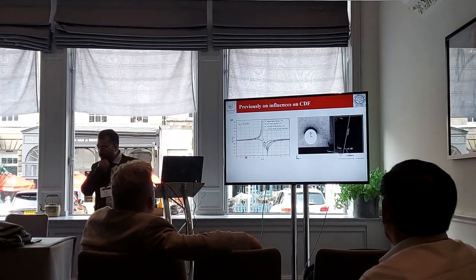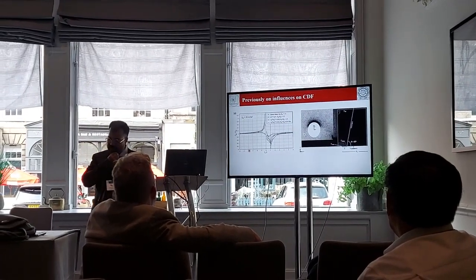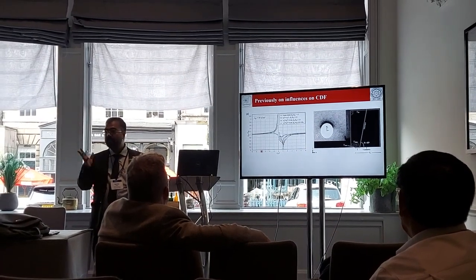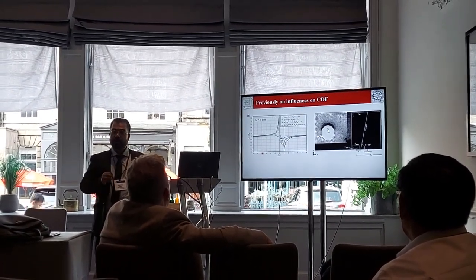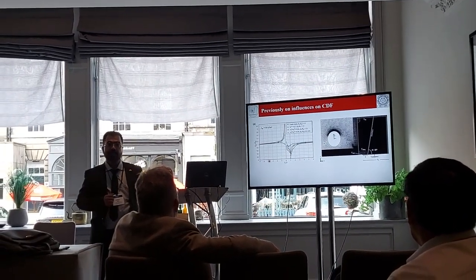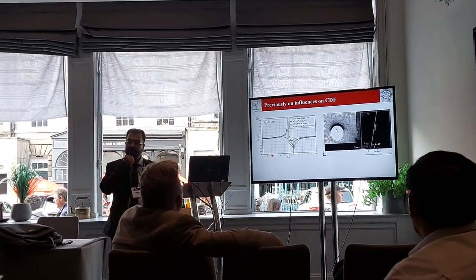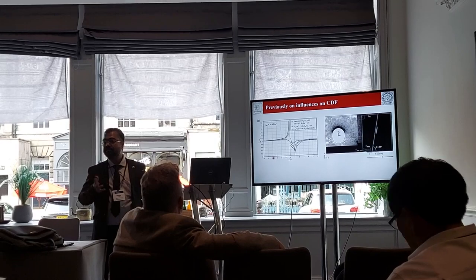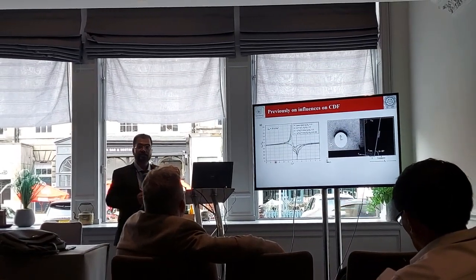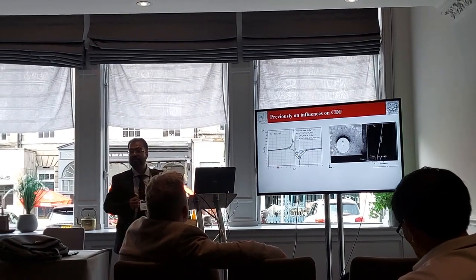Previous studies have shown that you can have material changes. In the reference configuration, you can have changes in the elastic modulus. For example, if you have steel on one side and titanium or something on another side, which has a very drastic change in elastic modulus. The other change could be that the elastic modulus is the same but the yield strength is different. The third one could be a combination of these. Of course, if the strain hardening coefficient has a change, that will also matter.